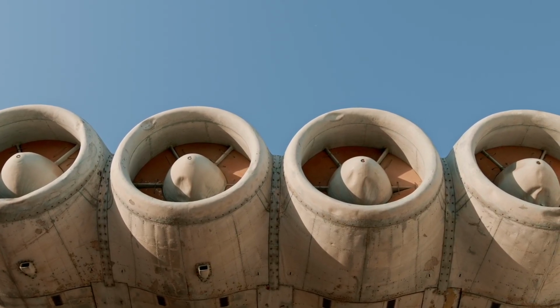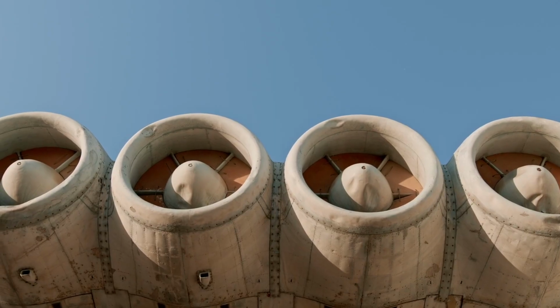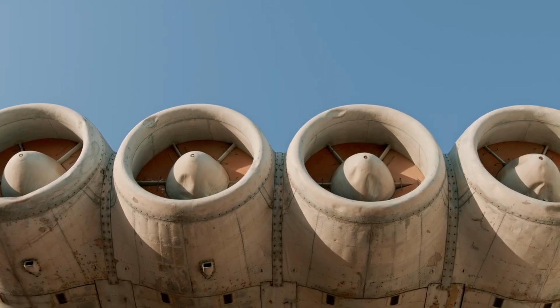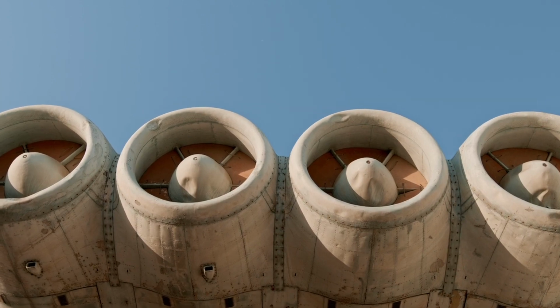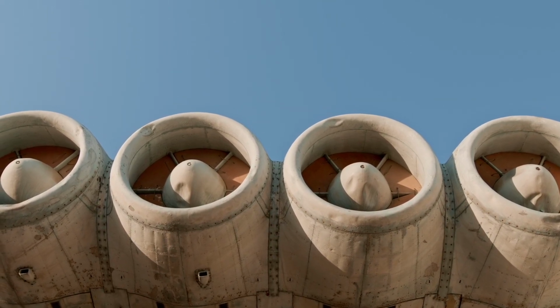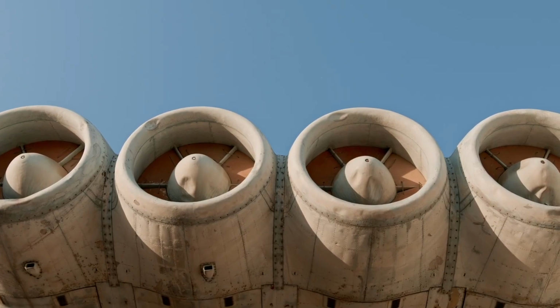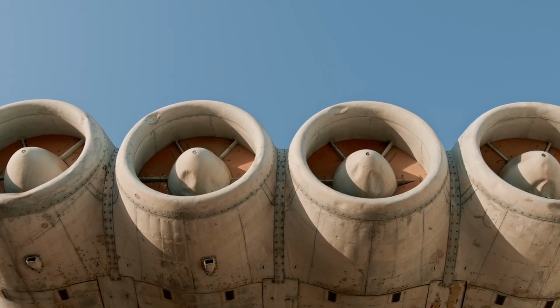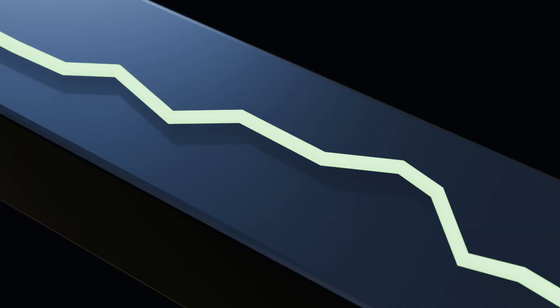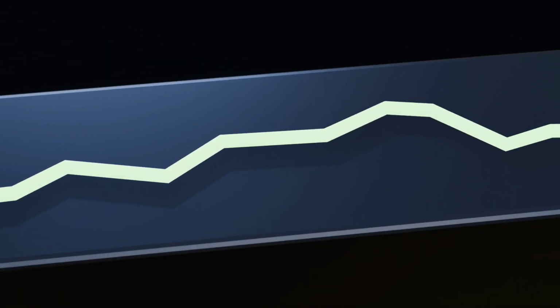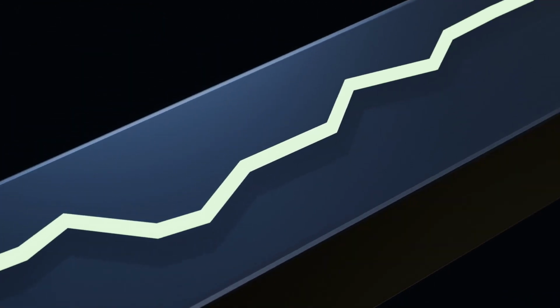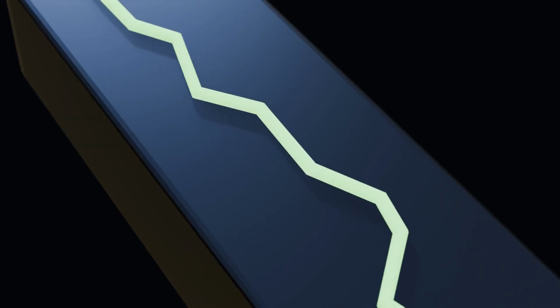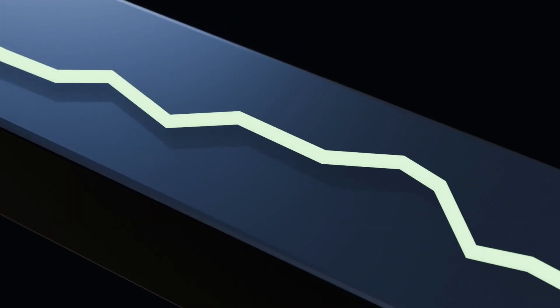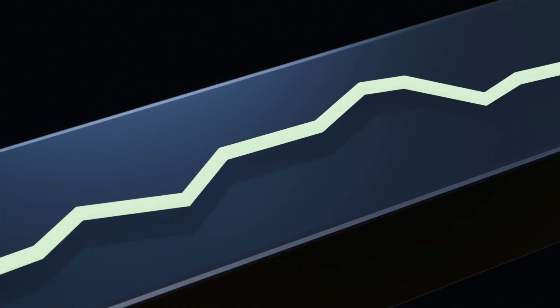The limitation is baked into the physics. Penetrant only finds flaws that break the surface. Seal that crack under paint or peen the surface closed and the dye has nowhere to go. It's also unusable on porous material because the entire surface would bleed. Swap the visible dye for a fluorescent one and you get fluorescent penetrant inspection, FPI, read under ultraviolet light in a darkened booth. It's the standard for engine rotating parts like fan discs, compressor discs and blades because it resolves indications a visible dye would lose.